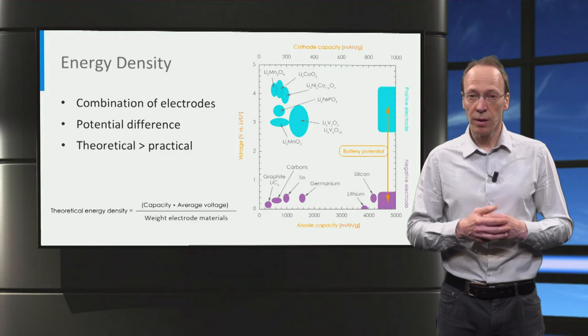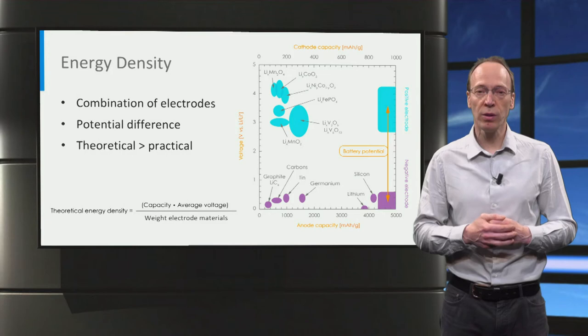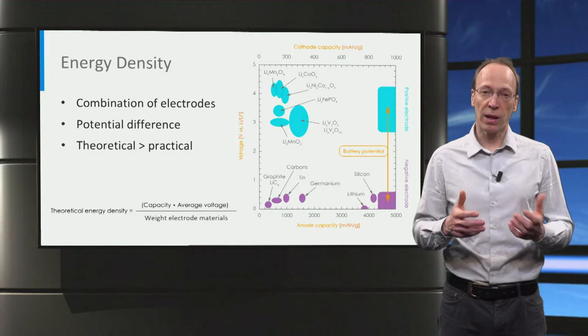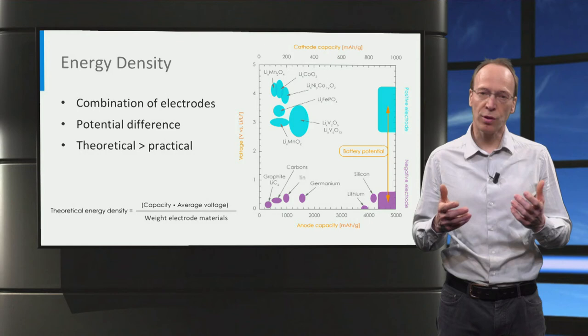This is because of the weight of the non-active materials, including the electrolyte, current collectors, and packaging. Both the specific capacities and average potentials of existing electrode materials are known, making it possible to calculate the energy density of any combination of electrodes. The potential of electrode materials is typically referenced to that of lithium metal, which is conveniently set to zero as reference potential. This has no consequence because the battery voltage is always a difference between electrode potentials.